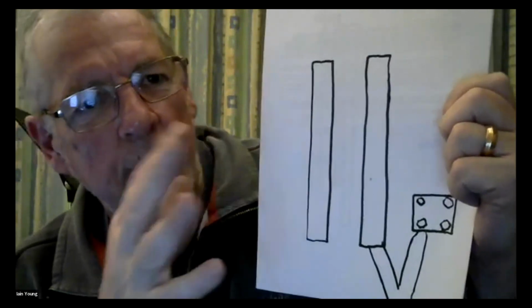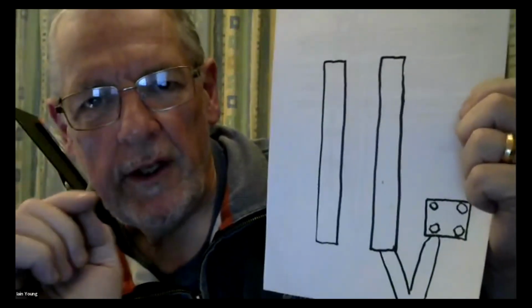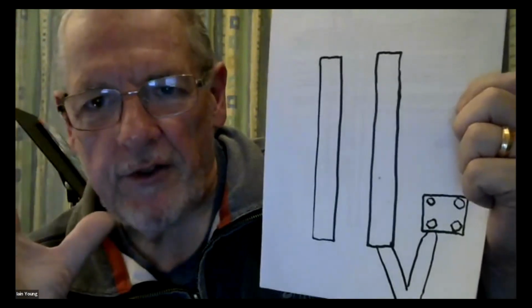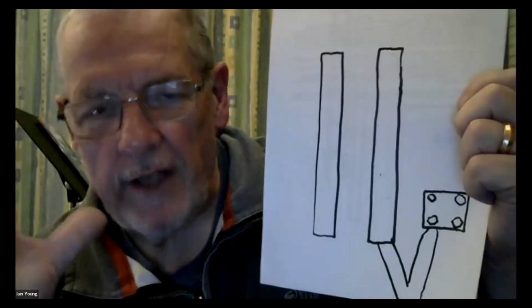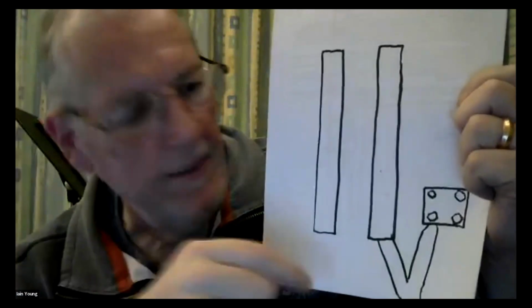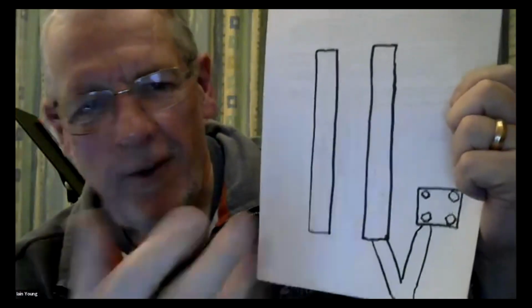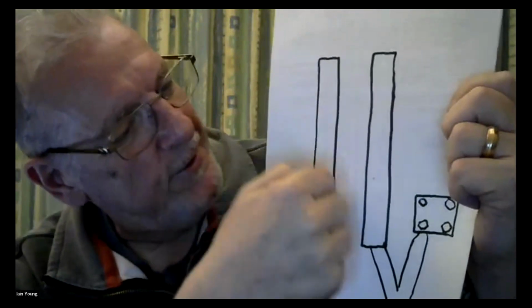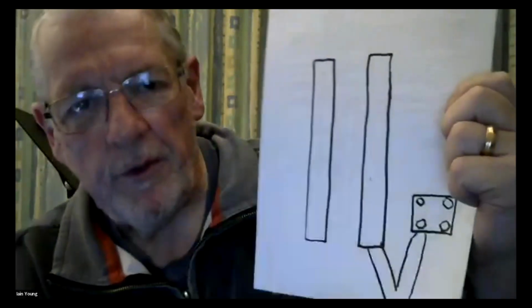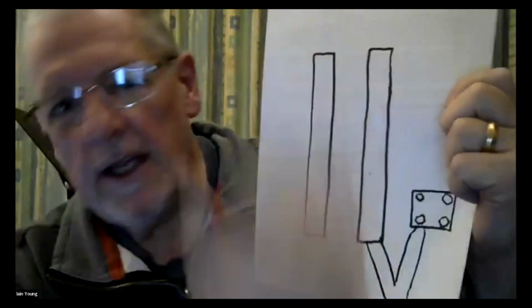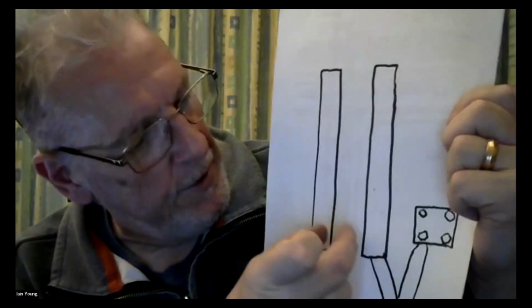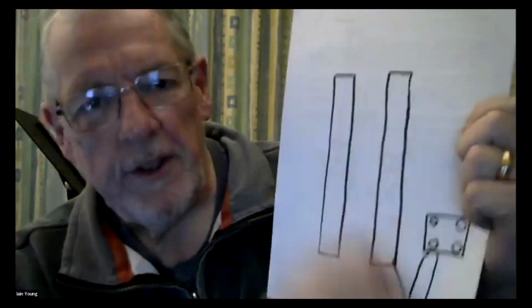But in the process of melting out the wax, the temperature of the flask gets up to 750 odd degrees Celsius. The brass tube would soften, and when the metal went in, the tube would just bend and do exactly the same thing. So now we put stainless steel tube in there, and the metal can cast around it, and that works a treat. But like I say, the thinner it gets, the more that becomes an issue, particularly with blind holes. Right, okay, so I'm just on to the next bit.